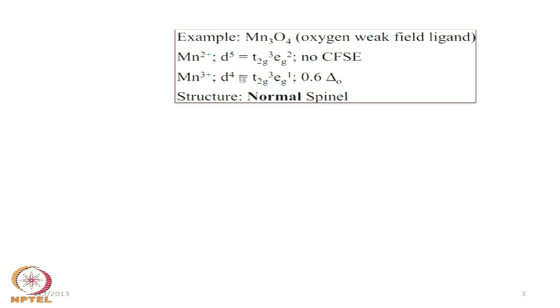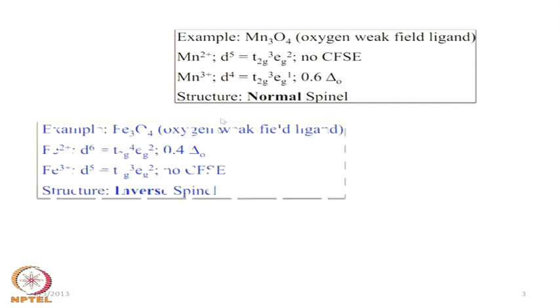But for manganese 3+, which is a d4 arrangement, that means t2g3 eg1, one electron is removed from the eg level. As a result, we have a corresponding crystal field stabilization energy of 0.6 delta O. So the structure would definitely be a normal spinel. It is a very simple calculation where we can calculate the corresponding CFSE of the bivalent metal ion in the octahedral field and the trivalent metal ion in the octahedral field.